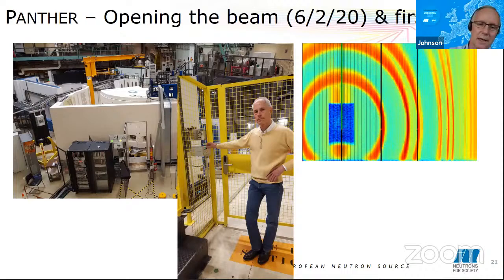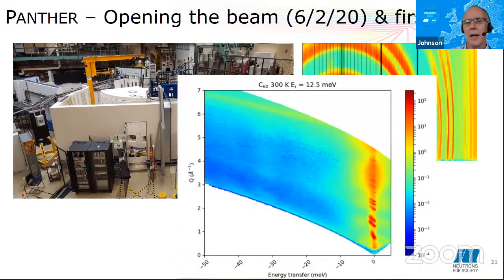So this is diffraction data, but we don't build a spectrometer just to measure diffraction data. We like to see S(Q,ω) maps like this. And if you have a trained eye, you can see the Bragg peaks, but also the acoustic phonons that emerge from the Bragg peaks, some quasi-elastic scattering, and then at higher energy transfer, some indication of optic phonons.